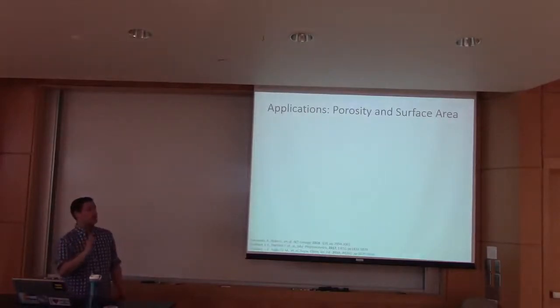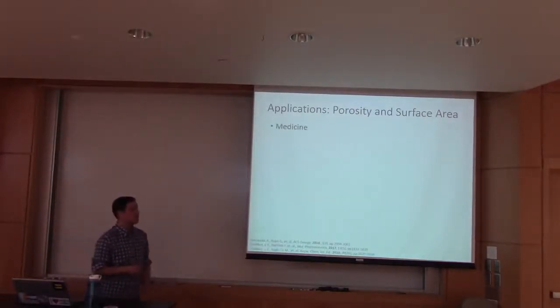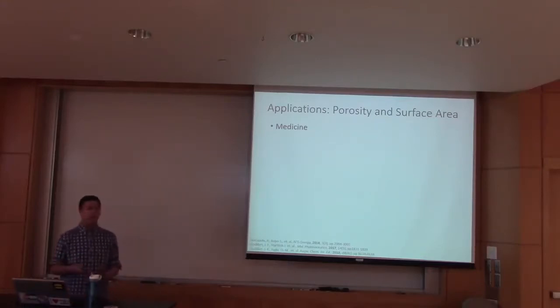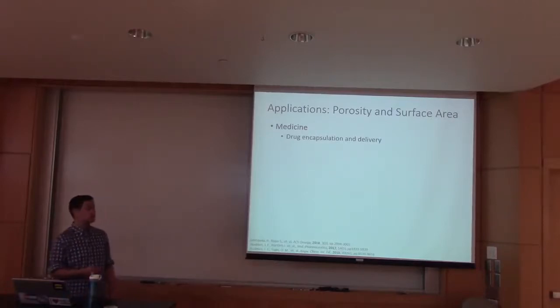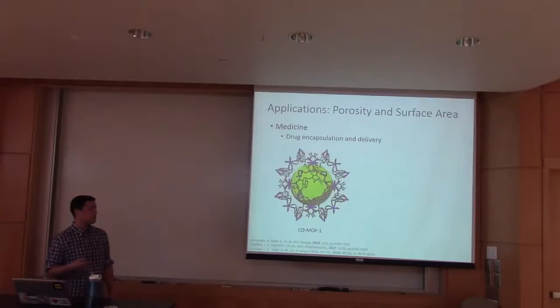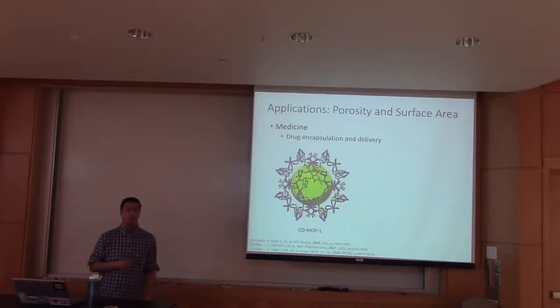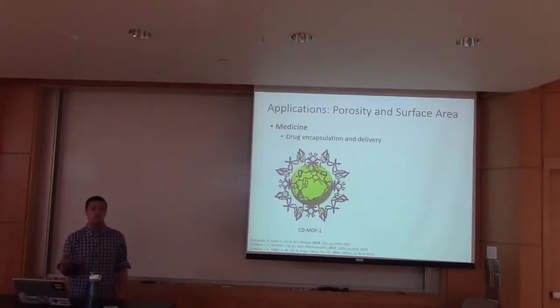And then one more interesting application in terms of porosity and surface area would be in medicine. Until recently, most researchers have considered MOFs to be way too toxic, both the metal centers and the organic linkers, to be used in medicine. However, researchers have been looking into using biocompatible MOFs that they've actually been able to encapsulate drugs with and use as delivery systems. Specifically, researchers, I think it was about 2010 or 2011, managed to synthesize this MOF, CD-MOF1, CD standing for cyclodextrin, which is a sugar that is enzymatically produced from starch.